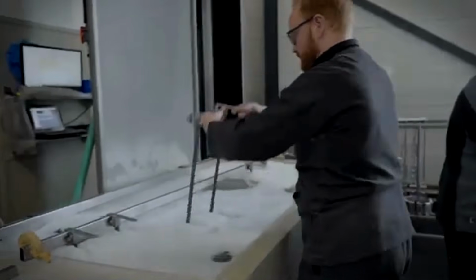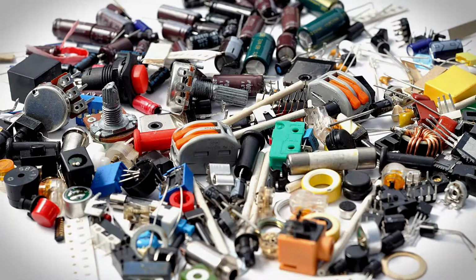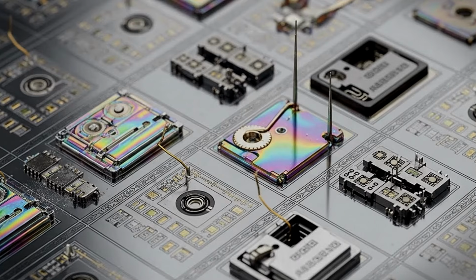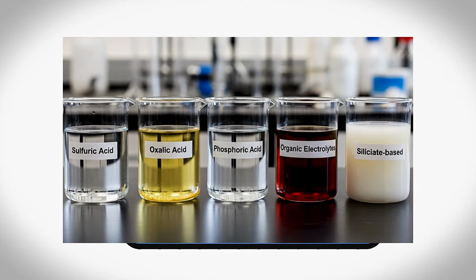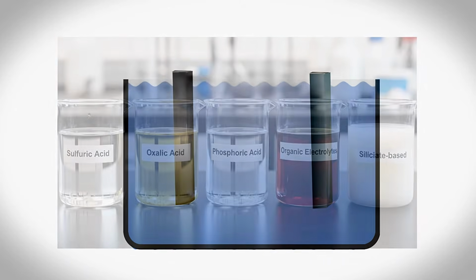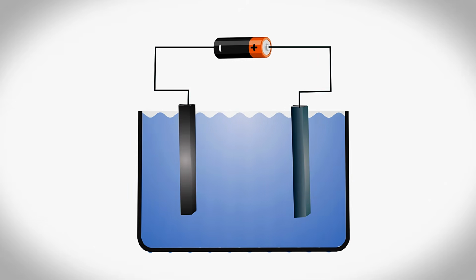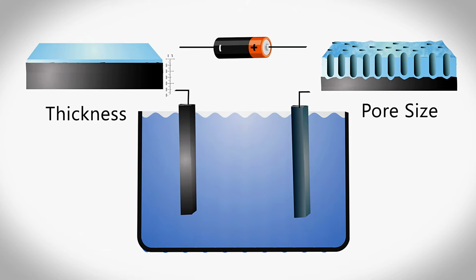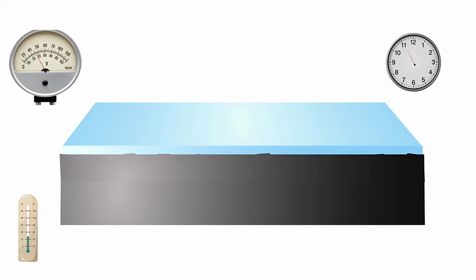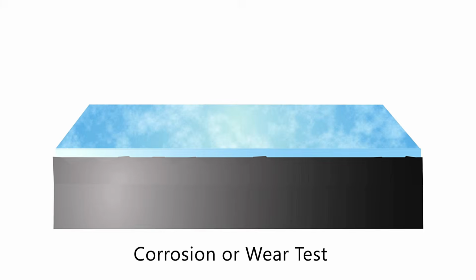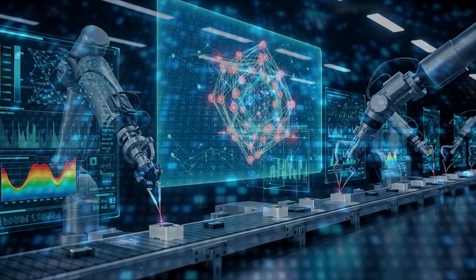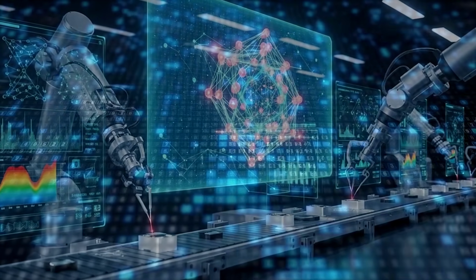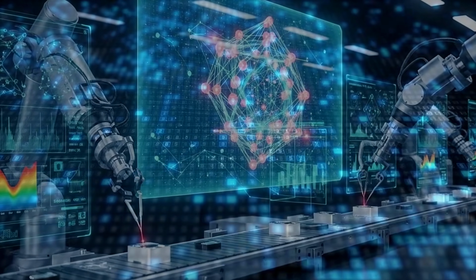If you want to design your own anodizing process, whether for aerospace parts, electronic components, or micro-electromechanical devices, the mental model is simple. Choose the metal and oxide you want and the active area you want to anodize. Pick the electrolyte that shapes how fast you build versus dissolve the oxide. Sulfuric, oxalic, phosphoric, organic electrolytes, or silicate-based for PEO. Then tune the field. Voltage, current density, pulse shapes to set thickness, pore size, and order. Then it's iteration. Vary time and temperature, measure thickness and hardness, test corrosion or wear, and feed the data back. Many modern lines can now use AI-assisted control, watching current and temperature in real time to keep every atom growing where it should.